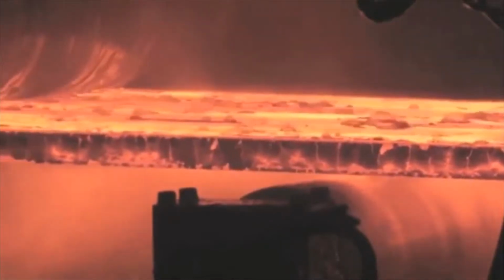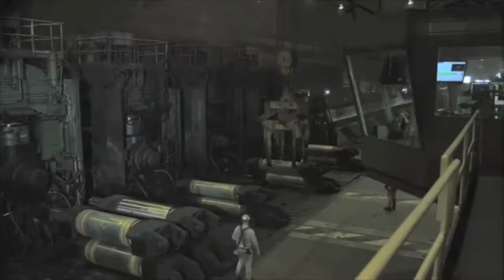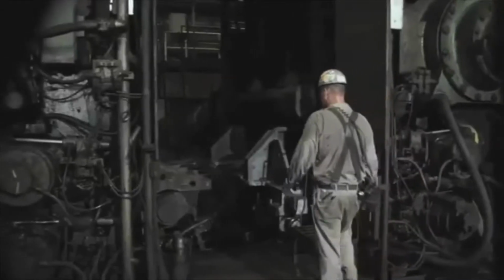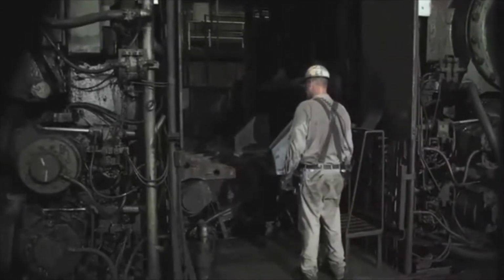Producing slabs up to 64 inches wide, the casters operate at a maximum speed of 230 inches per minute and process 9,000 tons of steel in a 24-hour period. Going through a 2,400 gallons per minute spray of cooling water, the slab is completely solid in 24 seconds and has an exit temperature of 2,100 degrees. After being sheared to length, the slab goes through one of two tunnel furnaces where the steel is reheated to 2,150 degrees before going to the hot strip mill.